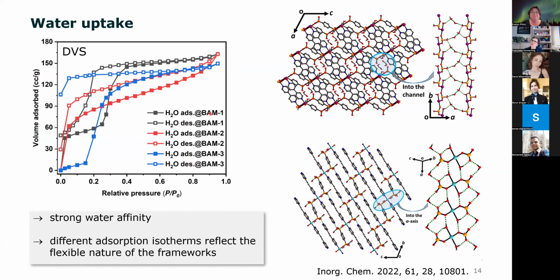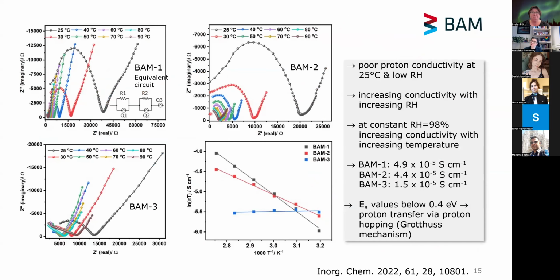And then in the next step, we also checked whether they show a decent proton conductivity, and without going into too much detail, we could see that at higher temperature and higher relative humidity, there is a fairly good conductivity, and we could also derive the type of mechanism by which the protons are transported here. So you can see that it is an easy access to new materials, and these materials are then also directly useful for certain applications.